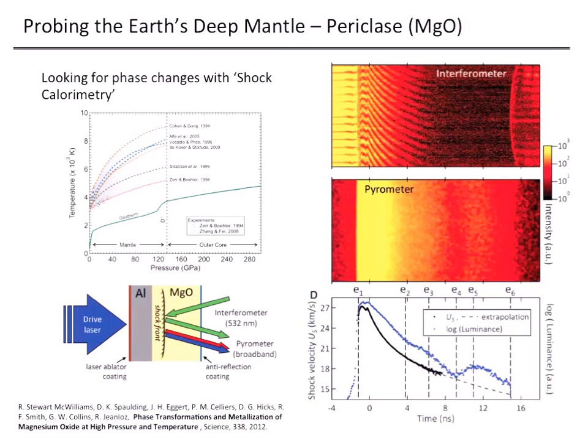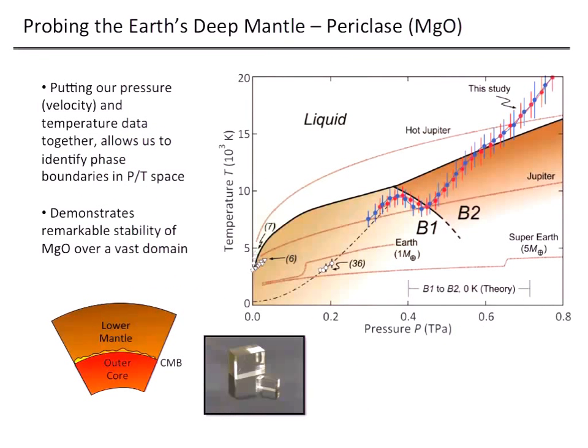The shock velocity decays smoothly with time because we put in this short laser pulse. But you can see that the thermal emission has structure in it, and this structure tells us that something's going on in these places. Indeed, what we conclude is in the decaying shock experiments, we go up to about 800 GPa, or about 0.8 terapascal, and we decay down. These subtle changes in slope actually turn out to reveal crossing the melt curve, we believe, in the B2 phase, and also crossing the B1-B2 solid phase transition boundary.